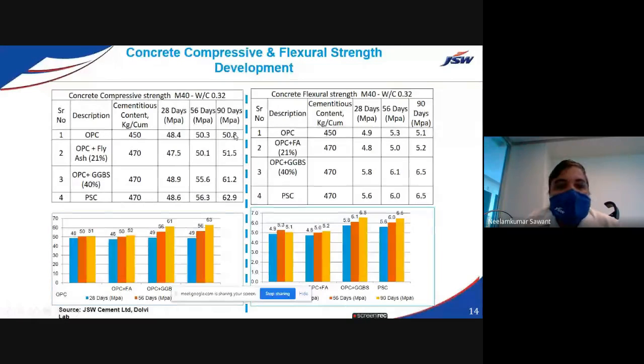If I am going to cast M40 of concrete with control water cement ratio 0.32, it gives about 51 MPa, and if I am using PSC or the blending of OPC plus GGBS, it gives nearly 61 to 62 MPa. Means you are getting over here 10 to 11 MPa more. So this is definitely will give the additional strength as well as durability for your concrete. So on the right hand side also you can see over here, these are the flexural strength. As far as flexural strength is also concerned, there is an enhancement in the flexural strength.